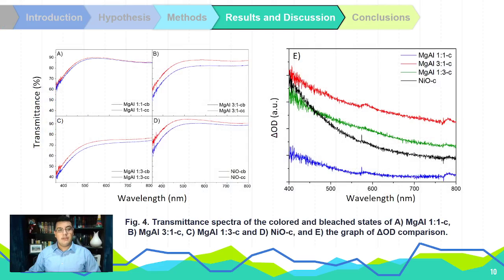Lastly, we present the results from the electrochromic test. On the left side, we can see the transmittance of the nickel oxide films, both in their colored and bleached states. It can be appreciated that all of the films show a lower transmittance in the colored state and a higher one in the bleached one. On the right graphic, we compare the change in the optical density of the films, and we can see that out of our three samples, two of them have a greater optical change in the visible region than that of the undoped material, confirming our hypothesis.